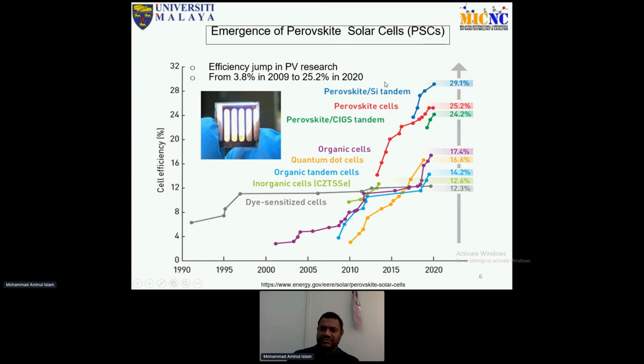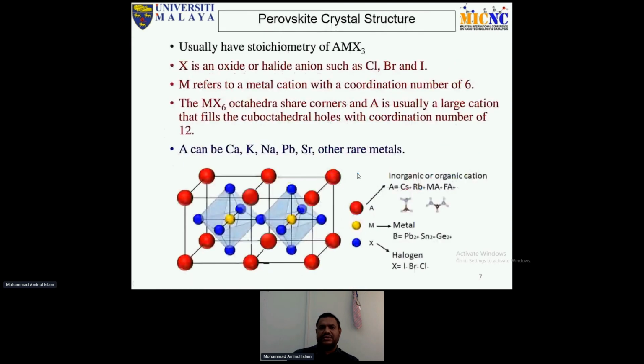So our main focus is making this solar cell stable under normal ambient conditions. And here you can see the lab-based solar cell, a photograph basically. The first perovskite solar cell was reported in 2009 with 3.8% efficiency. Now it has come to 25.2% within almost 11 years. So it's a revolution. We said that the main layer of a solar cell is the absorber layer, and in a perovskite solar cell, the perovskite layer is the absorber layer. So this is the main layer.